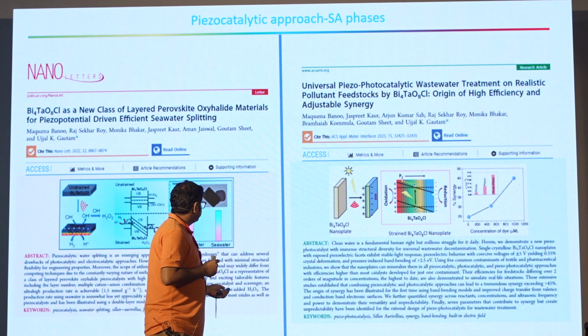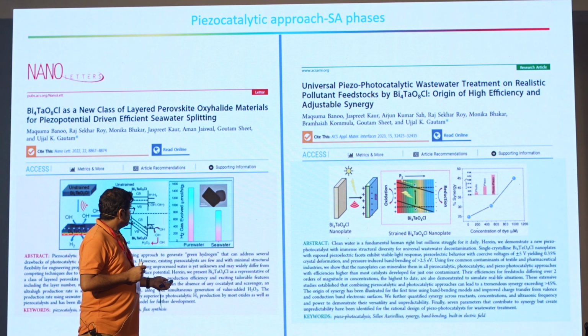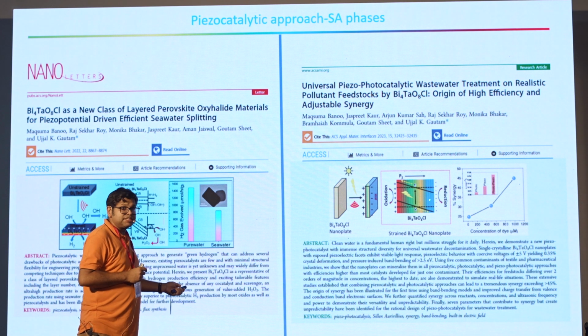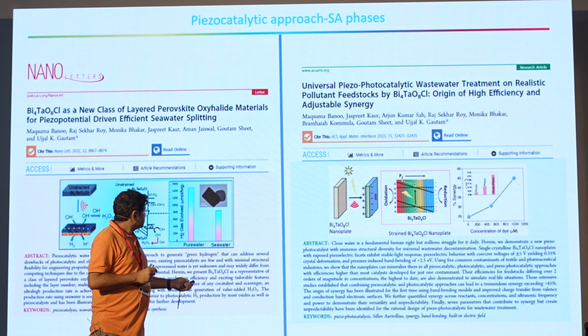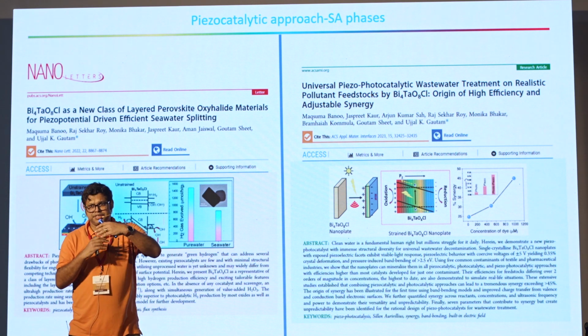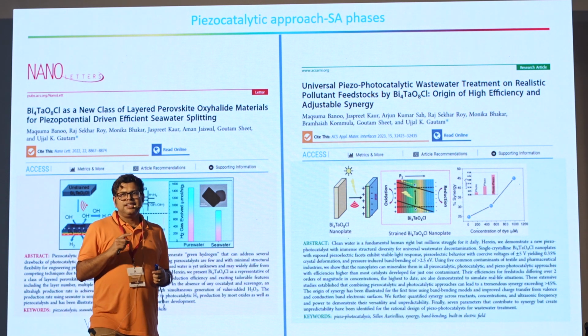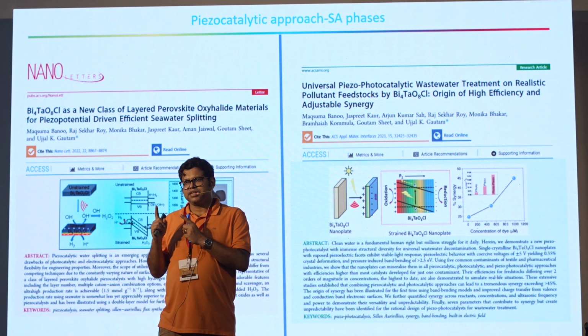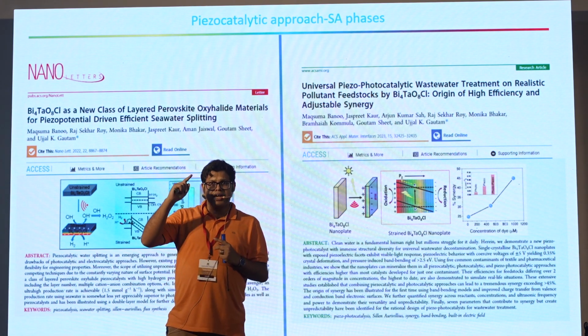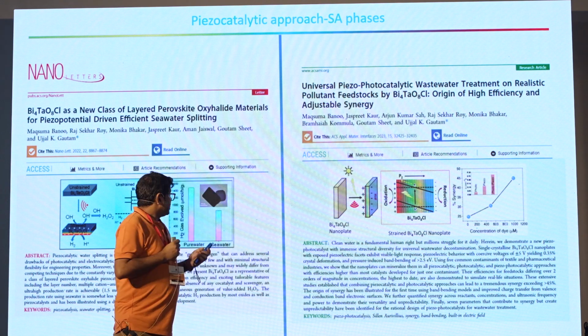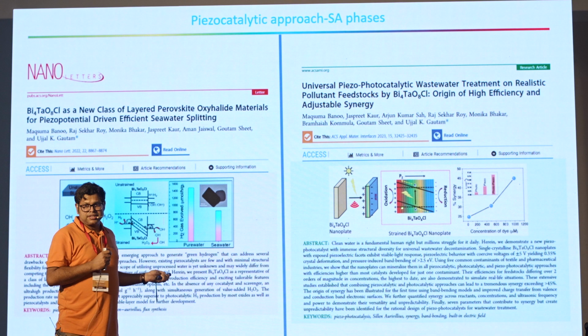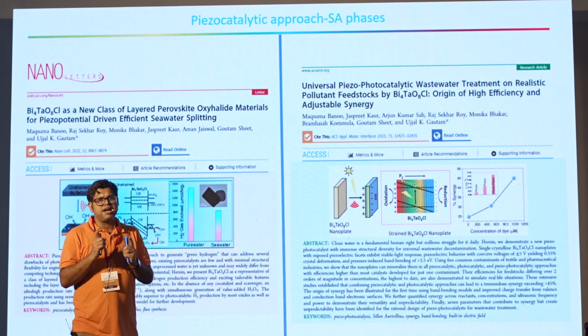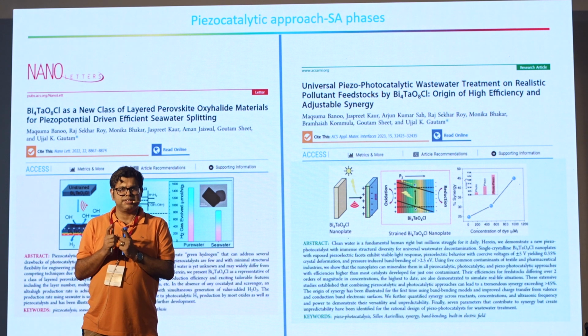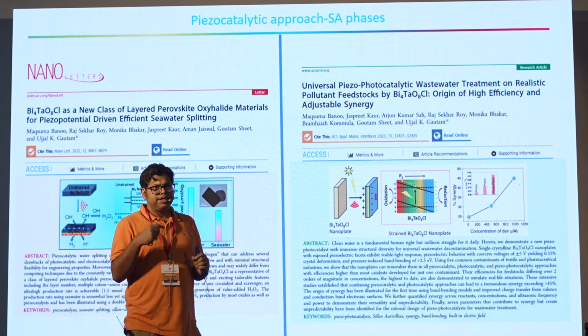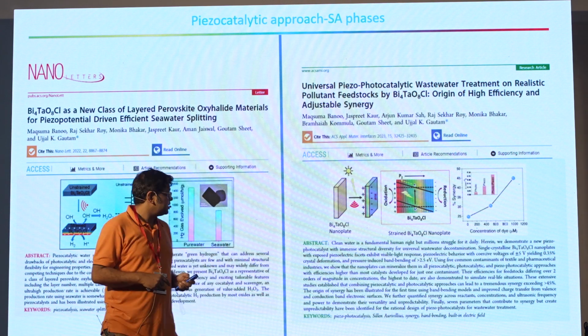As a consequence, within the crystal, if you assume this is the crystal, the energies bend. It's called band bending. So this is the conduction band and this is the valence band, or you can say this is the LUMO, this is the HOMO. They bend within the crystal. As a consequence, you can use any material for oxidation and reduction reactions because you are not limited by the reduction potential of your catalyst, because the reduction potential changes when you put pressure. It changes automatically. So if you have a centrosymmetric or non-centrosymmetric material, if you put pressure, you can use it to do oxidation and reduction reactions.